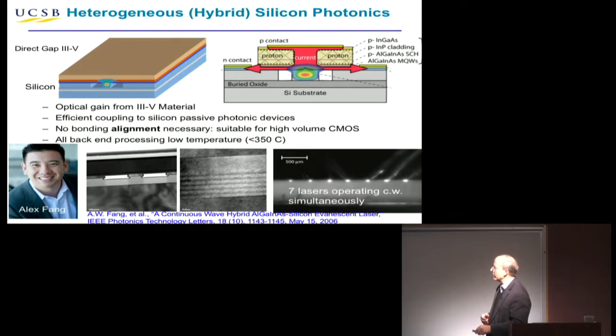So this is the work Alex Fang did for his thesis, and just an example. So you have waveguides in silicon. So again, the silicon waveguide loss is lower than indium phosphide or gallium arsenide. And part of the mode extends up into the 3-5 layer where we can have quantum wells and get gain or absorption or modulation or detection out of those structures. And so here's just a picture. This is actually every third laser. There's actually 21 lasers here, but we probed every third laser just to give an example of laser integration. So that's the general process.